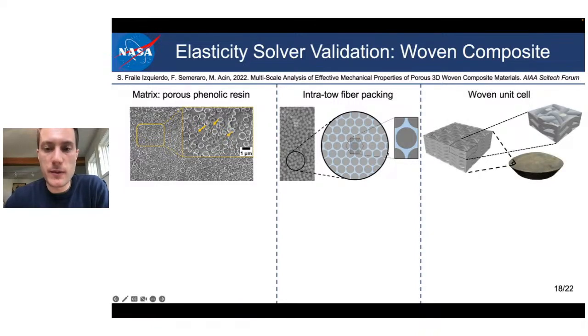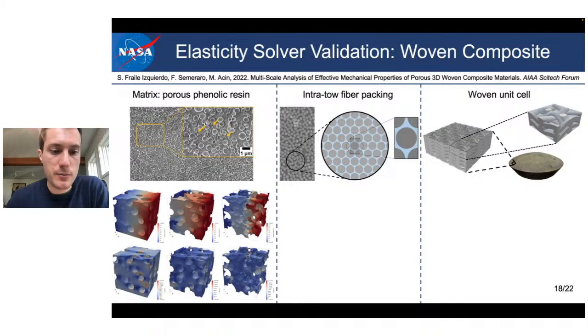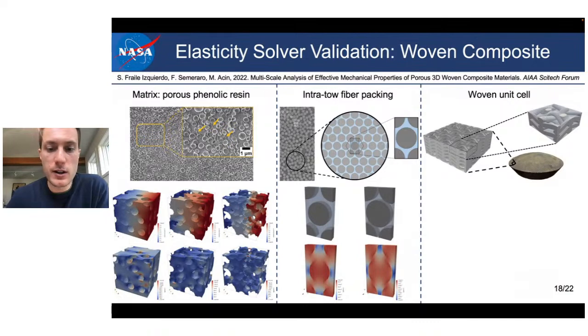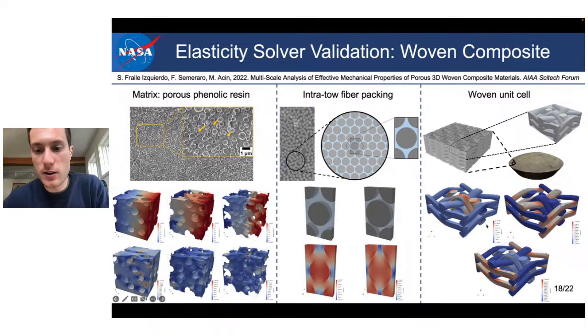And then finally, we use these properties in an actual woven unit cell of the tows and the phenolic phase for the void space. So we also did some parametric studies on the porosity of this phenolic resin and how the elasticity varies according to this porosity, as well as how the elasticity varies according to the fiber packing. And finally, these are the results of an artificially generated unit cell using the properties that we've computed at the matrix scale and the fiber packing.